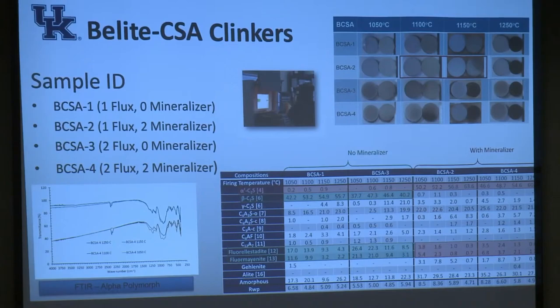And so CSAs are commercially manufactured. They are manufactured around 1250 degrees C, so obviously at a lower operating temperature than Portland cement. So there's energy savings there, fuel savings as well. And the clinker that comes from a CSA, that rock that's rolling out of the kiln, is actually much softer than a Portland clinker, so it takes less energy to grind. So overall, it is a less energy-intensive cement. It's not used as standalone cement in the materials world. It is often added to Portland cement as a sort of set accelerator or modifier.